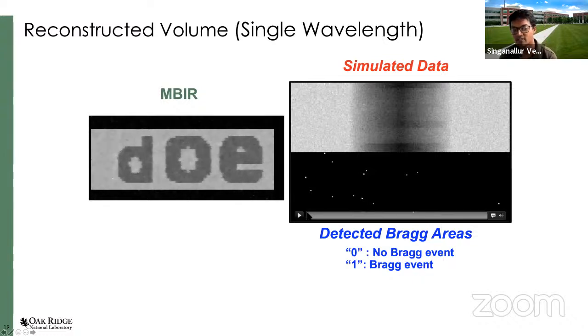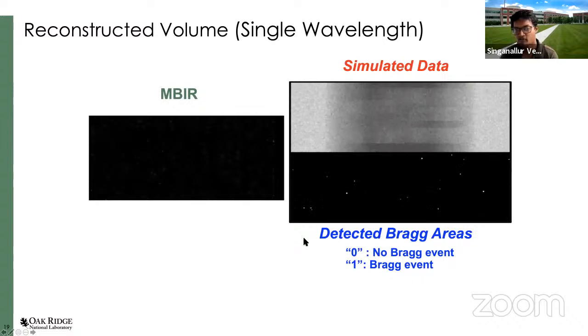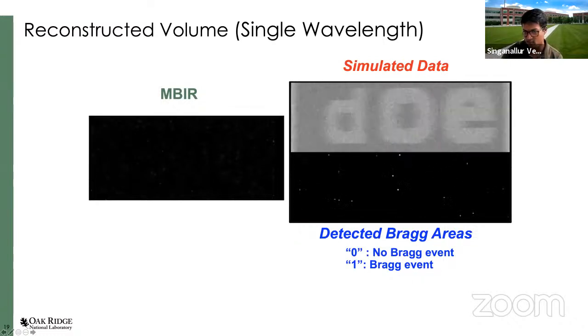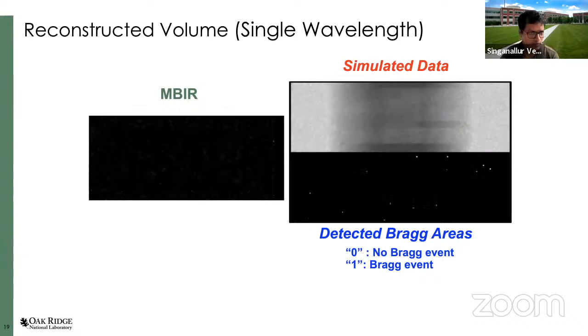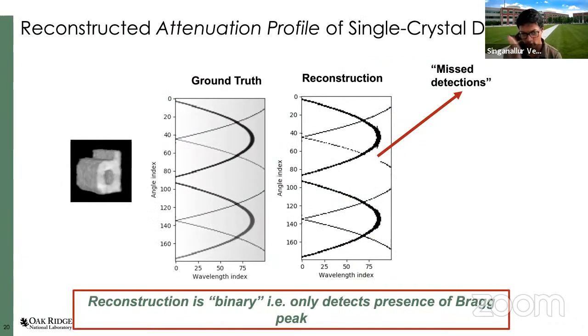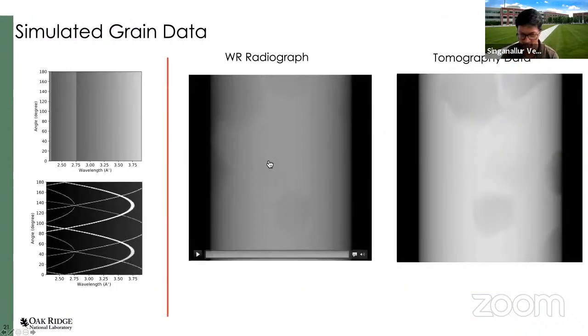And the nice thing is we are also able to, at the end, identify which measurements themselves were impacted by this Bragg scatter. Now you can go back and start correlating each of the individual domains to the Bragg scatter events. If I take the 3D reconstruction and segment out chunks, I can now say when it went into the Bragg condition. So you cannot clearly reconstruct the attenuation at every angle and wavelength, but you can see when it went into the Bragg condition. You can do that across wavelengths, and you can reconstruct what I call a spectral signature. So you have morphology and some kind of spectral signature.